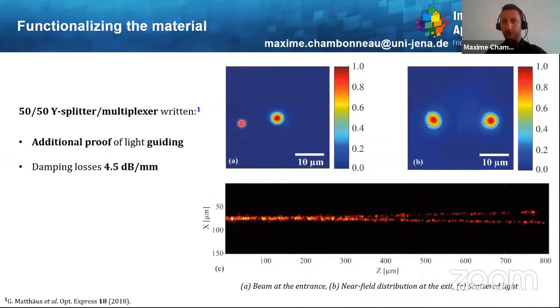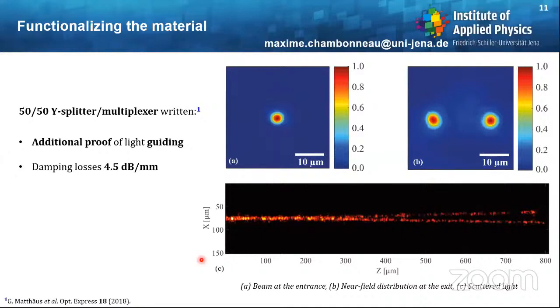It is also possible to not limit ourselves to waveguides, but also to Y splitters, which are often called multiplexers. So the idea here is to inject light inside a waveguide and then have two other branches. So the light is split in two. You can see on this figure on the right that we have a 50-50 Y splitter, which is actually an additional proof of light guiding. And the damping losses are on the order of 4.5 dB per millimeter.